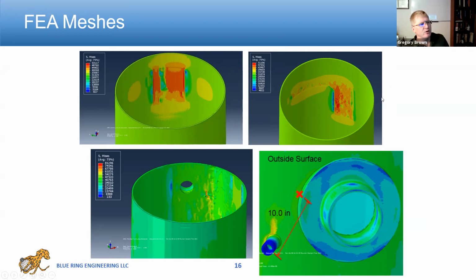As it turns out, these locations passed the level 3 assessment rules. We'll talk about those assessment rules in the course. But the other corrosion that you can see on the bottom was located near these nozzle locations. Anytime you have corrosion at a nozzle or other structural discontinuity, the level 1 and level 2 assessments will not apply. It automatically causes you to do a level 3 assessment. In this case, that's what we did. You can see some higher stresses occurring at the nozzles. As it turns out, this did not pass the level 3 assessment. So they went to a repair situation.